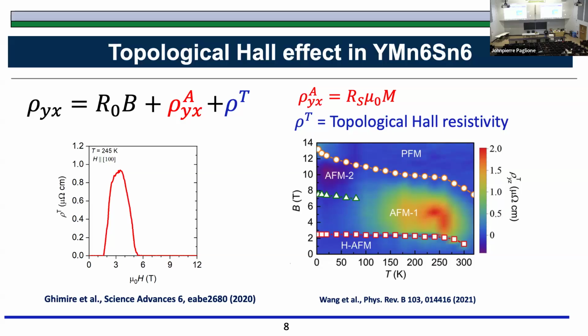See here, there is some structural part also. Because this kagome lattice is very two-dimensional, what happens is that when you put a spin in a completely two-dimensional system, there is a theorem called the Mermin-Wagner theorem, and what it says is that you cannot have an ordering of spins in a perfectly two-dimensional system, which now is not entirely true in some material cases, because recently in completely two-dimensional systems, people have found ferromagnetism because of the anisotropy and so on. But that theorem still holds, meaning that it generates a lot of fluctuations. So this is a manganese system, and the manganese is fluctuating highly, and that fluctuation is enhanced by the temperature. So at high temperature, you can get this scalar spin chirality. So the structural part was also important, not just the kagome part here; being two-dimensional was important in this case to get this state.